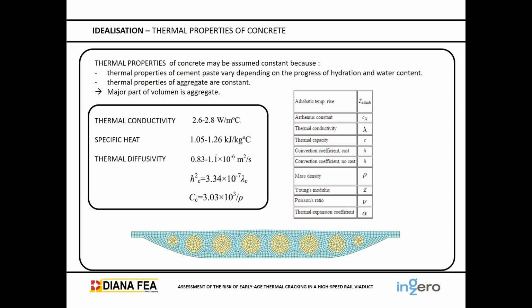And the other thermal properties of concrete we assume to be constant, because the thermal properties of cement paste vary depending on the progress of hydration and water content, but the thermal properties of aggregate are constant. So the major part of the volume of the concrete is aggregate, so they recommend making it constant. We introduce the thermal conductivity, the specific heat, and the thermal diffusivity. These are the parameters that have to be entered in the model.